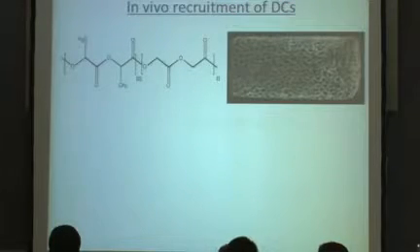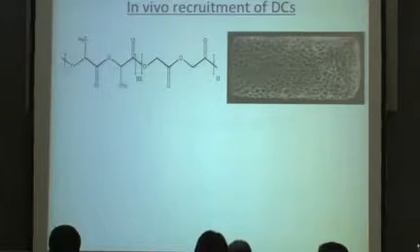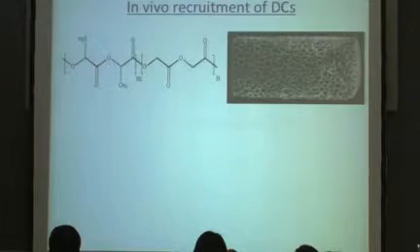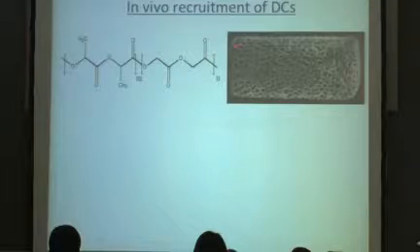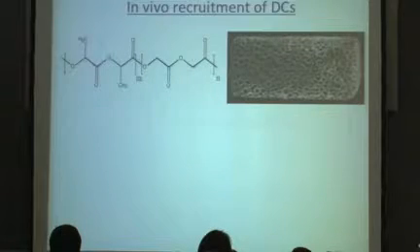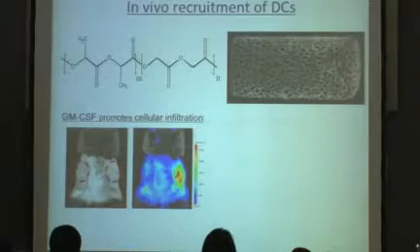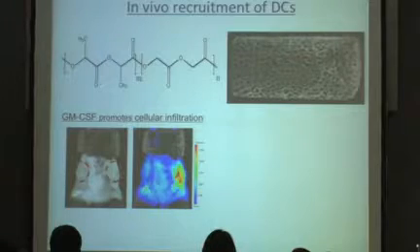So we took the most widely used biodegradable synthetic polymer, polylactide-co-glycolide, that many of you are very familiar with, and we borrowed a technique we had developed a number of years ago to make highly porous materials. It was a technique we borrowed from the microcellular plastics field, and we wanted these materials to be highly porous so a lot of cells could crawl in and live inside this device for some period of time while we appropriately educated these cells.